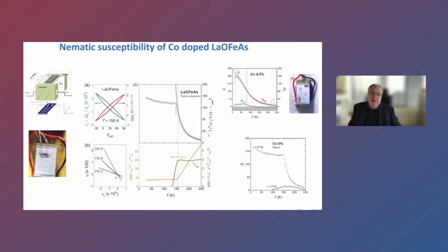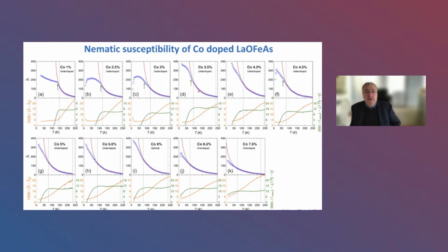So 1 over this nematic susceptibility follows a straight line, and this shows you just how good this fit is. So, parent compound, no surprise, divergence at the phase transition. Such experiments you can now do on the entire series of crystals, and that's shown here. So you start from the underdoped compounds where you still see these phase transitions.